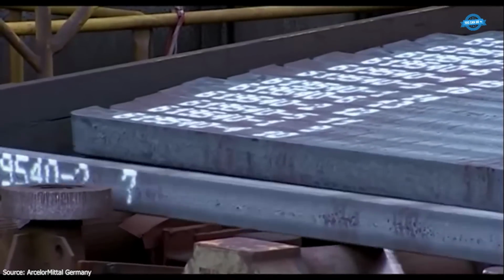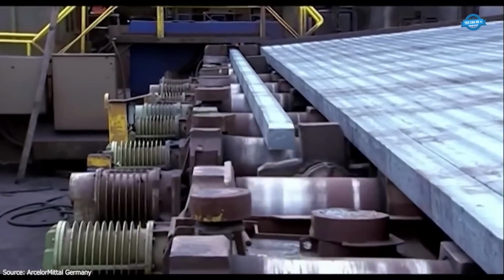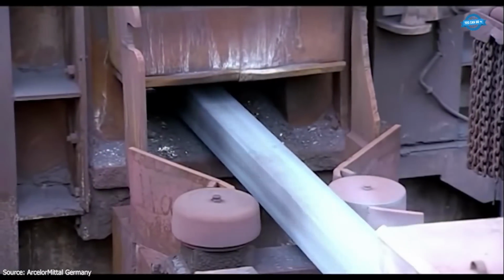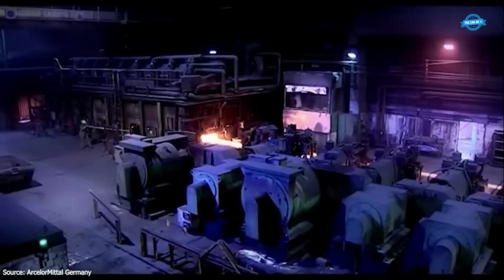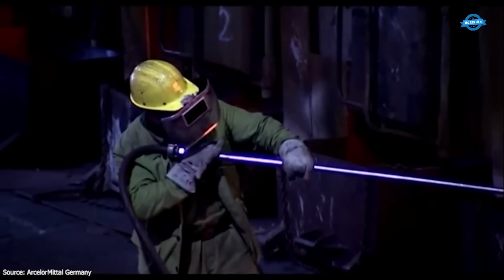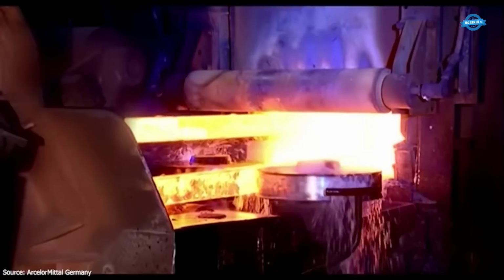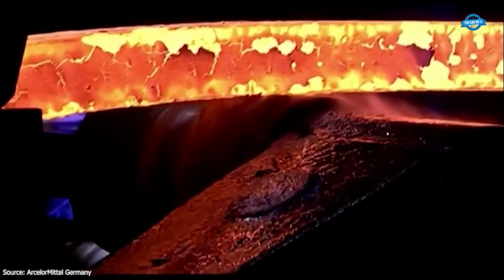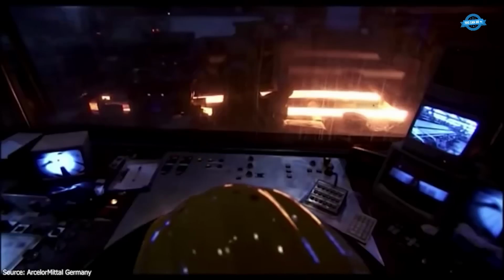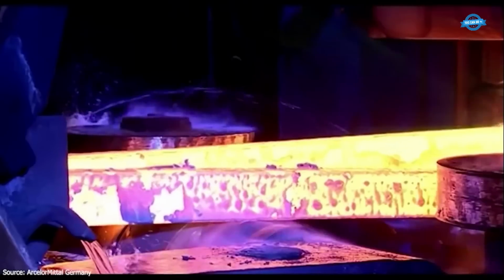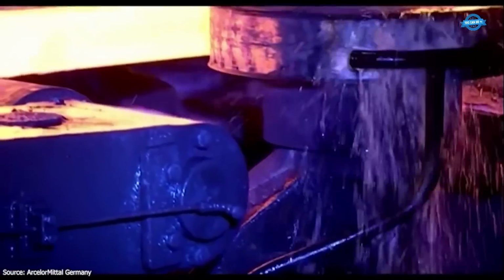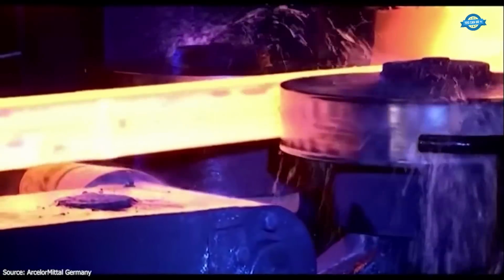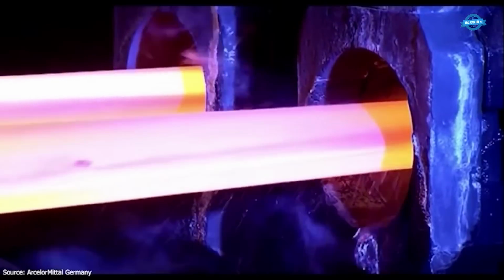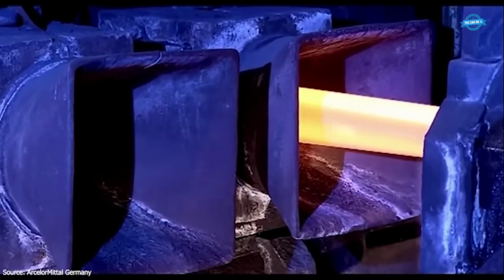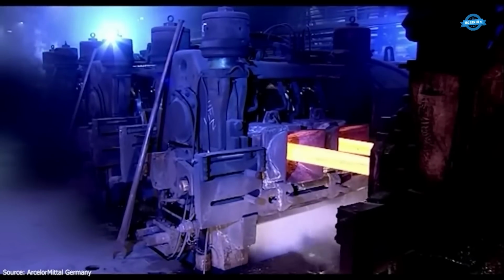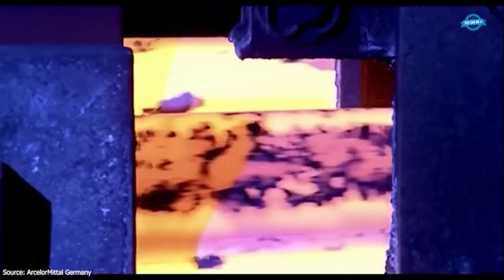Sampling is performed automatically and analyzed by an optical emission spectrometer to fine-tune the chemical composition. Once the desired composition is achieved, molten steel is tapped into ladles, treated in ladle furnaces for temperature adjustment, and prepared for continuous casting. Steel is poured through a distributor into 6 copper-cooled molds. The resulting billets can be up to 16 meters long and weigh up to 2 tons. They are rapidly cooled through water spray systems and cut precisely to the required lengths.